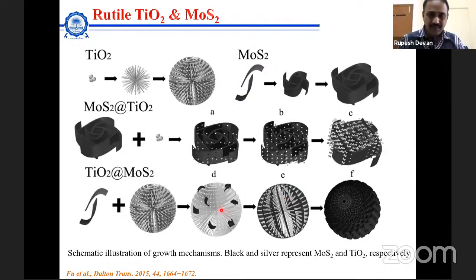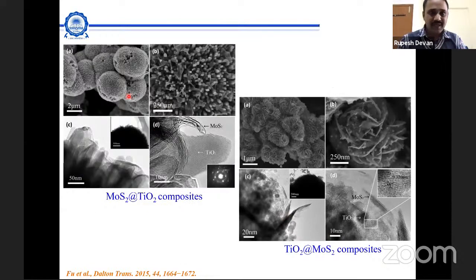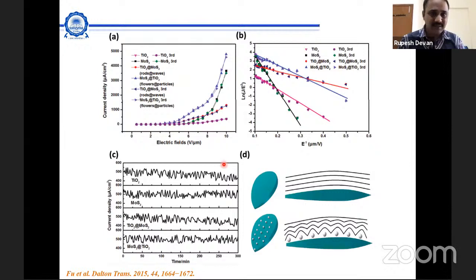That had not happened, but they covered the whole nanorod structure. So the nanorod became inside the structure, that means the shell, and this two-dimensional structure as a core-shell kind of thing. It looks like that, but they couldn't cover it properly, so it was lying like an island on these nanorods. If you look at the properties, they achieved a turn-on field that was quite higher, approximately 4 volt per micrometer, and the stability was not that good.